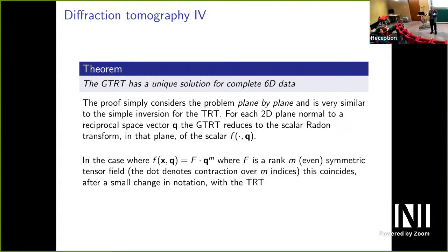But for the purpose of reconstructing, we're only going to take the values on a line, because for each absolute value of Q, the spatial frequency, that's a circle from the diffraction pattern, something happening on a particular length scale. And then we only take the value at the top of that circle to reconstruct the reciprocal space function for that length scale, as the value of Q. And we reconstruct the scalar. So again, it could be a bit wasteful because we threw away most of the data. But that means it has a unique solution, and so you happily go and do it numerically.